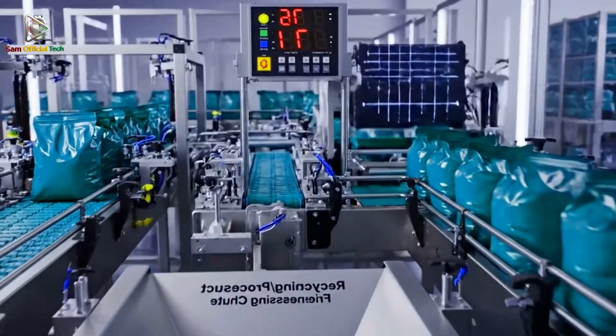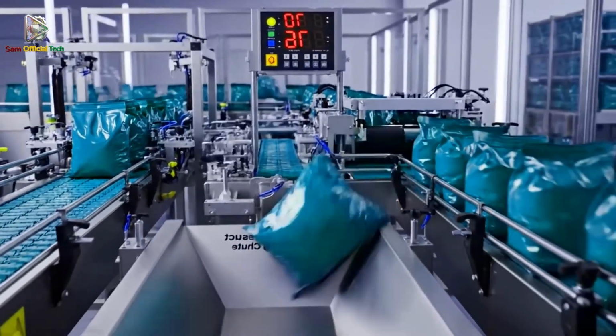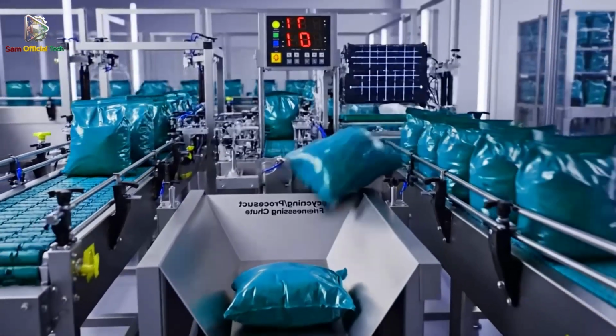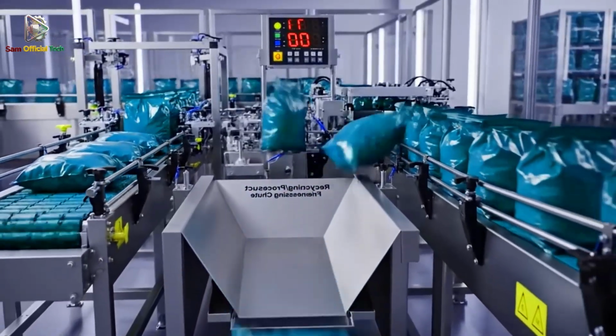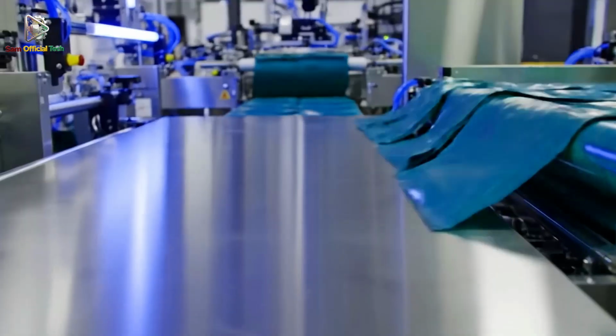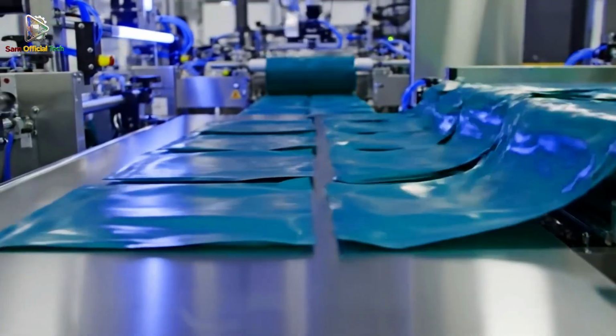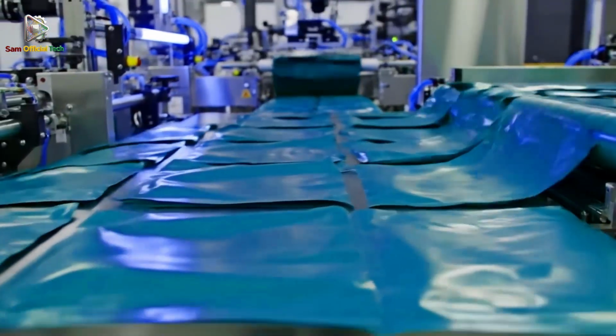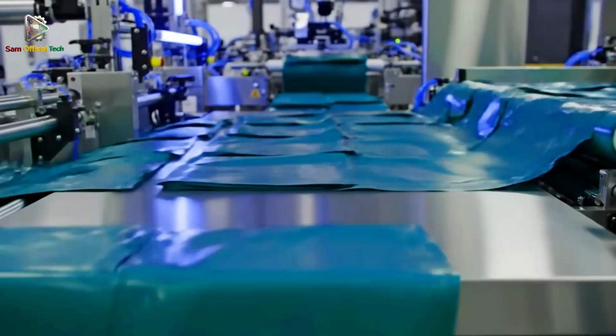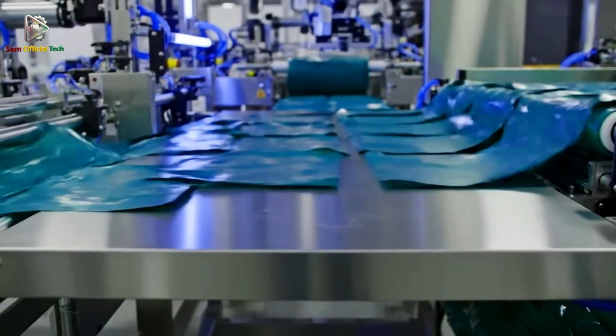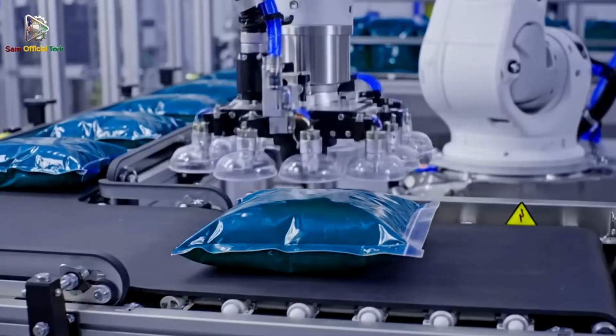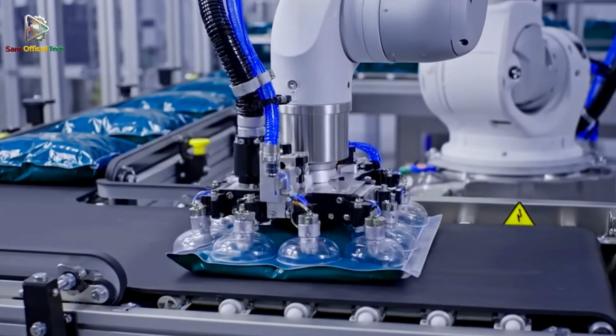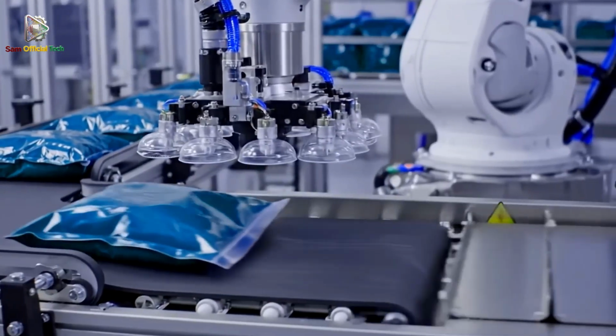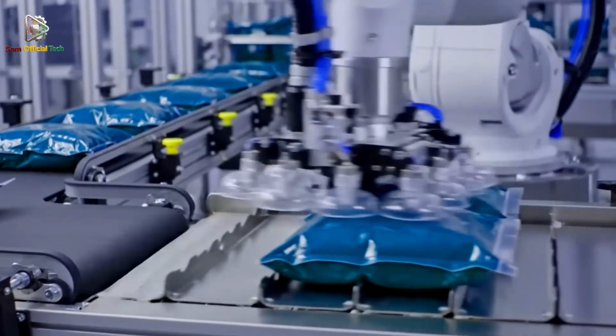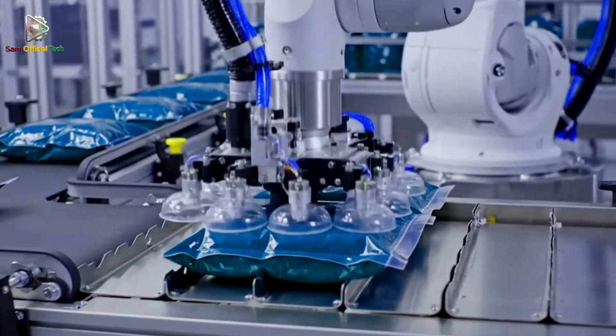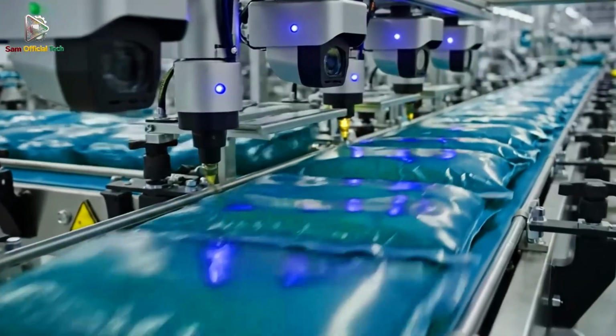The reason this process qualifies as high-tech is that it connects marine agriculture to materials manufacturing with tight tolerances. The factory uses spectroscopy and viscosity grading to standardize polymer performance, membrane filtration to hit food-grade purity, precision coating to control film thickness in microns, ionic cross-link chemistry to control water behavior, and forming technology to produce shapes that act like plastic without being plastic.